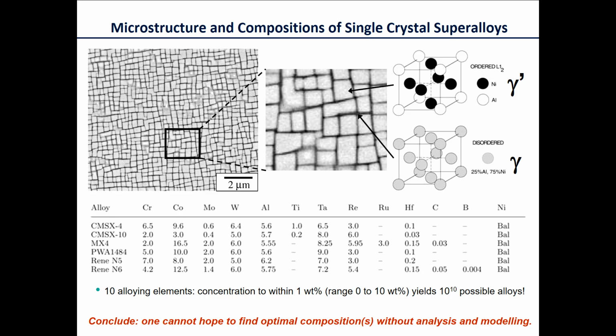Okay, so this picture here shows you that the microstructure of these materials is pretty beautiful, but also the key point here I want to make is that the alloys here that we use are pretty complicated in themselves. From a chemistry point of view, we add 10 or more different elements, typically needing to specify the percentage to very fine levels. And so actually you can see here that just from a simple thought experiment, it's not easy to optimize these materials from the point of view of trial and error. We need to have some kind of analysis method to optimize the materials. So I'm going to try to say something about that also in my lecture today.